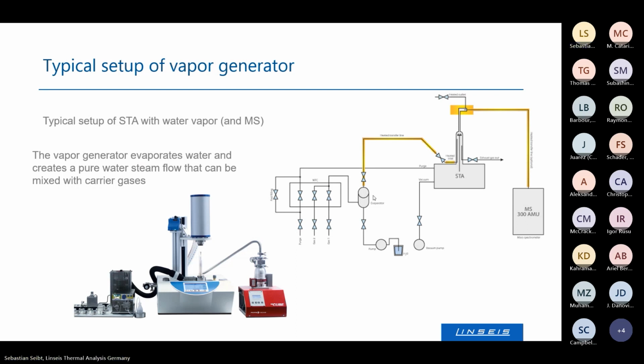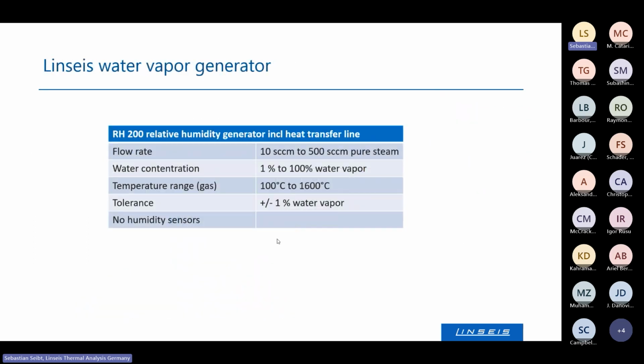However, if you use water vapor, the transfer line is always heated higher than 100 centigrade, around 200 or 300 even. You bring in the hot gas directly as water gas, and you also have a heated outlet, going into the condensation trap after the experiment. You can also still couple mass spectrometers, FTIR, whatever, via the heated transfer line. That's what we do regarding the vapor.